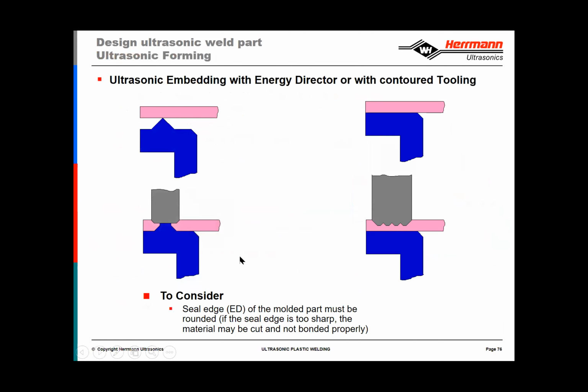The thing to consider here is the thickness or the loft of the fleece or the film that you're using. If it's a very thin film, we typically do not recommend the energy director design, but rather the design where the sonotrode is doing the embedding. If it's very thin, the film can sometimes be cut by that energy director. So in those cases, more often than not, we recommend that the sonotrode have the detail, a larger surface, to embed the film into the plastic part.